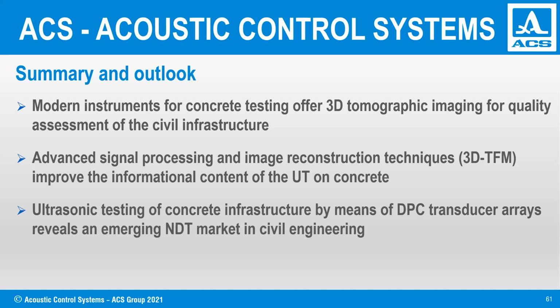But UT has another disadvantage. If your rebars, or let's say your defects, are too close to the surface, we have a so-called dead zone, a few 10 millimeters, maybe 15, 20 millimeters, where ultrasonic testing is blind. But georadar is a little bit more sensitive at the surface. So each instrument has advantages and disadvantages. I would say it is better to combine those two techniques.